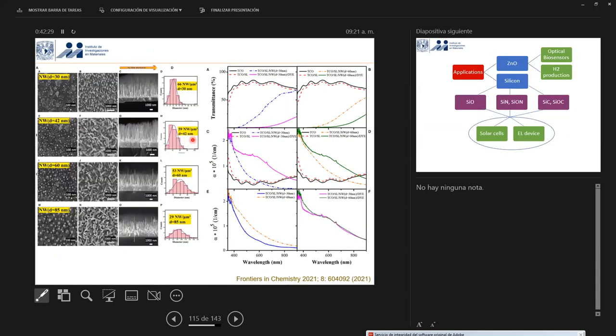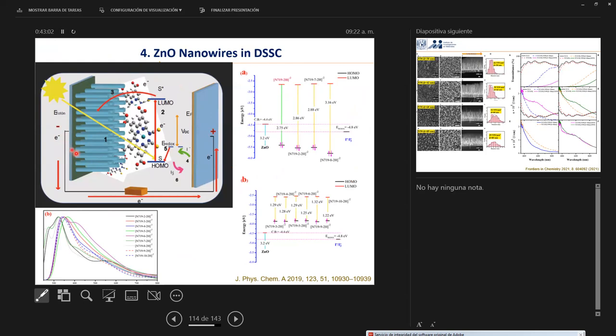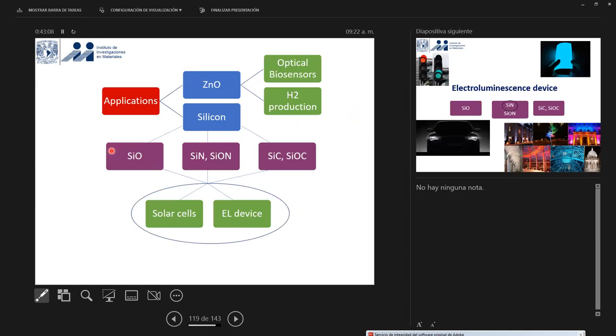And if we can increase the electron circulation, we can increase the conduction, we can increase the efficiency of the whole device. So what we did is, we grew different kinds of nanowires and nanostructures, by controlling the different morphological parameters in the earlier stages. And we found that we can control the diameter from 30 to 42 to 60 to 85 nanometers with different densities. Among all the different densities and diameters, we found this particular structure was quite good depending on the absorption limits. So now we are developing the whole structure with this particular diameter and density of nanowires, because we found that it could work as a good sensing device. And in this case, we can develop a high efficiency solar cell. So this was with zinc oxide nanostructures.